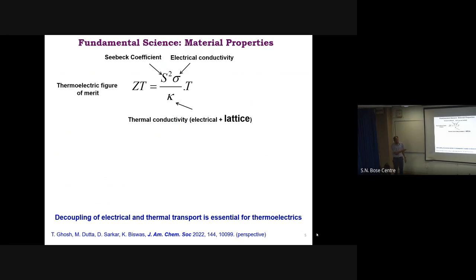Whereas the lattice thermal conductivity, which is carried by the phonons, is the intrinsic parameter of a material, and that is the only independent parameter in this equation, because the Seebeck coefficient and sigma are related by carrier concentration, as described by the Mott equation. So, can you decrease the group velocity of phonons or block the phonons in a high-density solid material? That is the challenge.